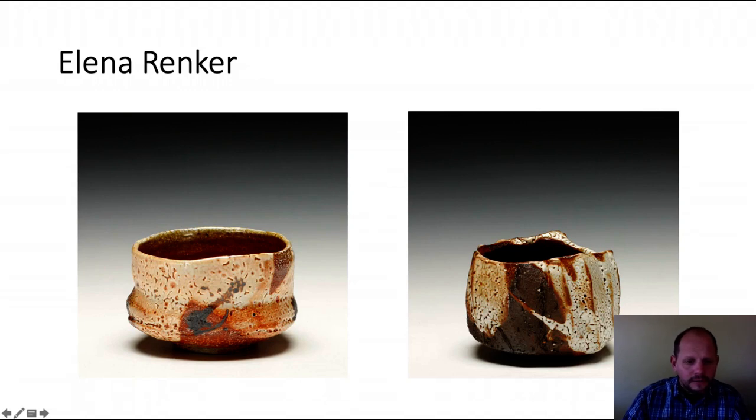You can see these really beautiful variations of iron piercing through the white part of the glaze, especially over here. These areas are really due to interaction between the glaze and the clay, and because the clay body is so dark, it's going to push those iron-rich brown to orange colors through.